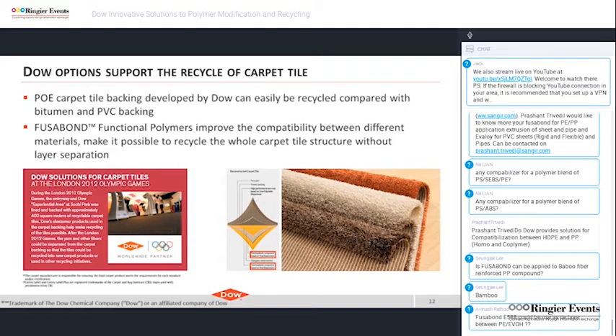Dow's solution on recyclable carpet tile is to use polyolefin elastomers carpet tile backing developed by Dow that can be easily recycled as compared to bitumen and PVC backing. Fusabond functional product is used as a compatibilizer to improve the compatibility between different materials, which makes it possible to recycle the whole carpet tile structure without layer separation.